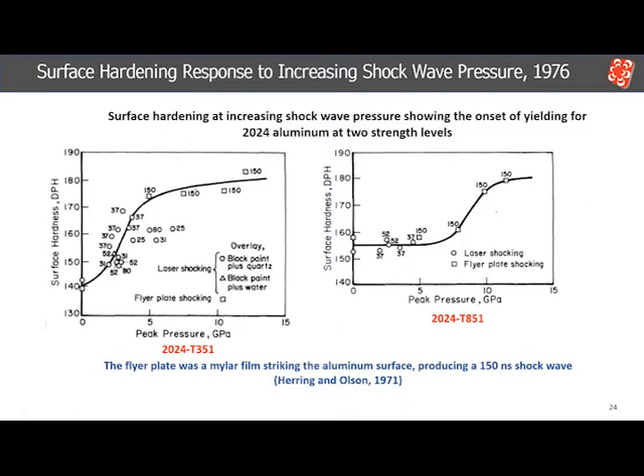In the left figure, hardening of the 2024 T351 begins to occur at a very low peak pressure and steadily increases up to what appears to be a maximum at about 165 DPH, or diamond pyramid hardness. For comparison, Herring and Olson performed flyer plate impacts on similarly aged 2024, whose hardness was very close to ours. Their flyer was a thin mylar plate producing a shock wave 150 nanoseconds long and square in shape. Their results are also plotted in the figure and slightly raise the apparent laser shock hardness plateau. For comparison, if you beat on the surface with a hammer, DPH 180 is the maximum hardness of these alloys.